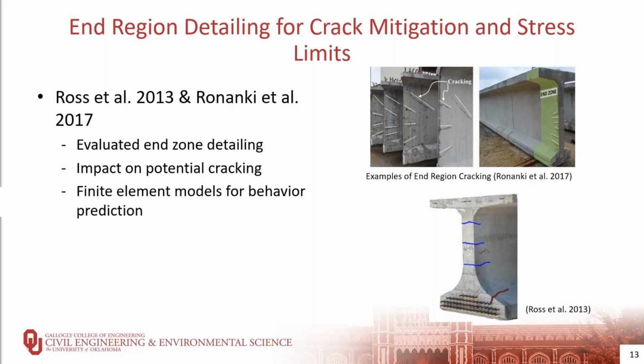The experimental work that they did in this project included load tests of 32 pre-tensioned precast girder specimens, where those specimens were loaded in 3-point bending and ranged in size from 28 to 63 inches deep. Analytical work in this project utilized the finite element analysis method, where the FE models were linear elastic and were intended to model the behavior of the end region prior to cracking.